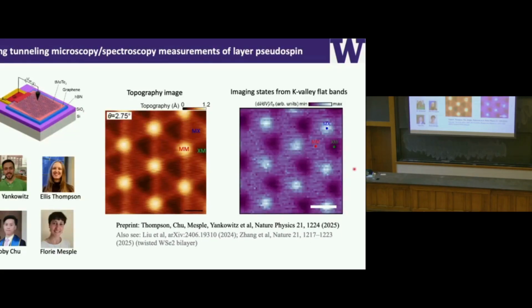And my collaborator, my colleague Matt Yankowitz, is actually now able to image these layer pseudo spins using STM. So here's a topographic STM image of a 2.7 degree twisted sample. And you can see these high symmetry points, with MX and XM. Those are the two domains, the layer pseudo spin I talked about. Then he also imaged the density of states from these flat bands, and it really shows that the density of states is localized at these MX and XM points.